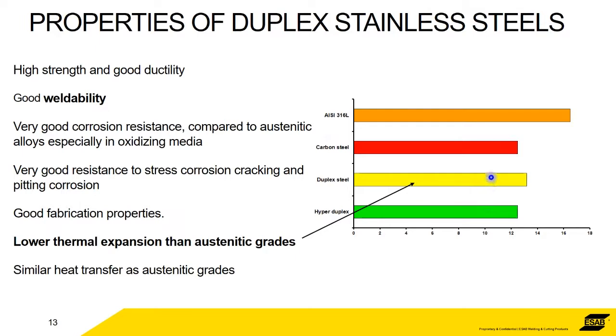If you look at the duplex steel family, it's only slightly more than carbon steel. So in that respect, it's easier to weld. The hyper duplex thermal expansion is just about the same as carbon steel. So even though you've got all these alloys going on, you've got 27% chrome in this one, for example, in terms of thermal expansion it's a lot less than austenitic grades, and it's around about the same as carbon steel. So in that respect, it's easy to weld.